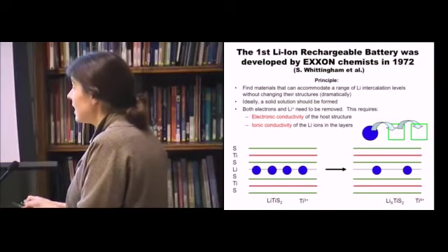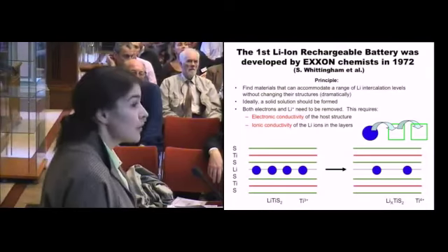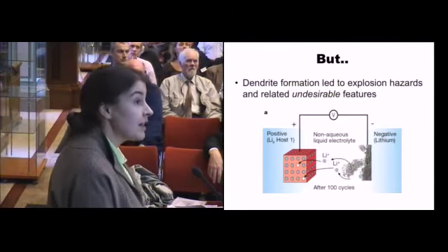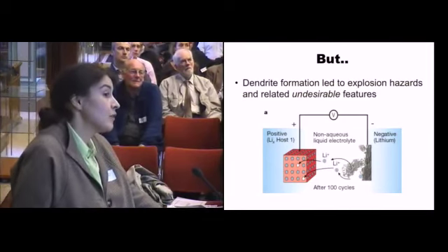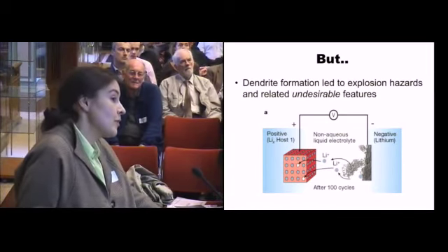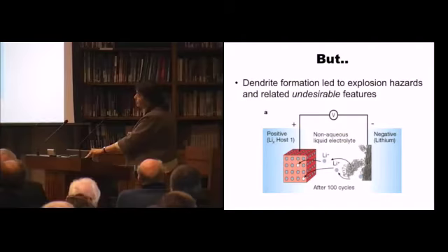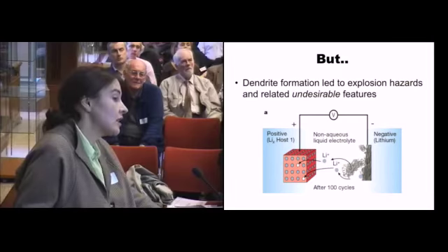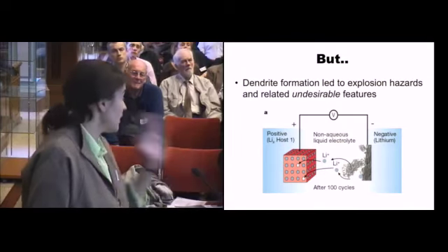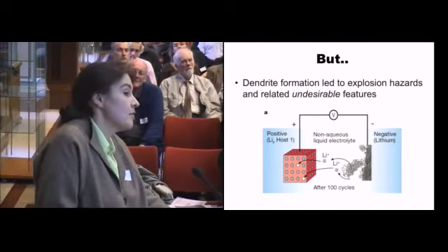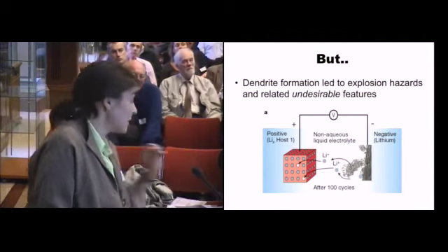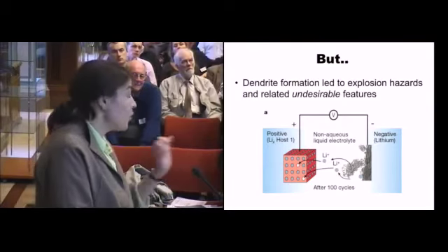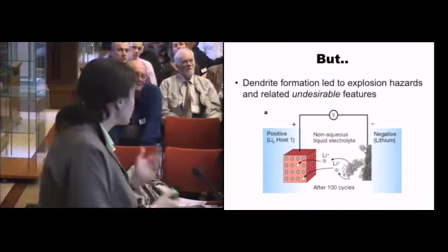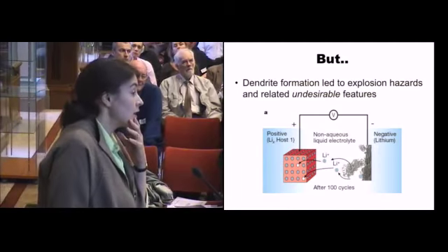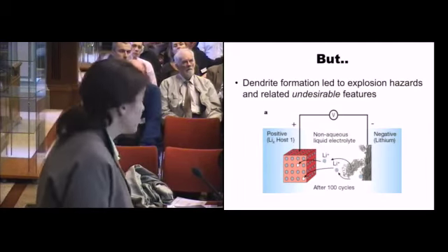But unfortunately, he coupled up the lithium-titanium-sulfur system with a lithium metal on the other side. And so instead of the lithiums going backwards and forwards nicely, when you pull the lithium out of the lithium-titanium-sulfur system, instead of plating nicely on the lithium metal, it formed these dendritic structures. And even though you put a so-called separator, typically a porous polymer membrane, these dendrites can force their way in. Once they see small little pores, they can ram their way through, just in the same way that ivy gets through concrete, short-circuit the battery, and cause the explosions that I showed you in that Macintosh laptop.